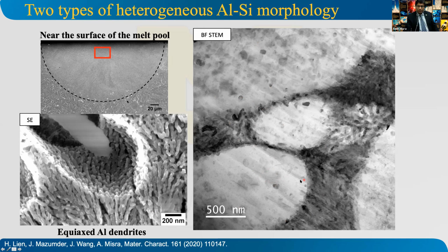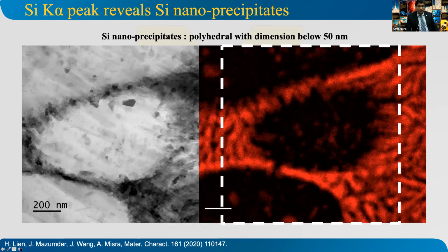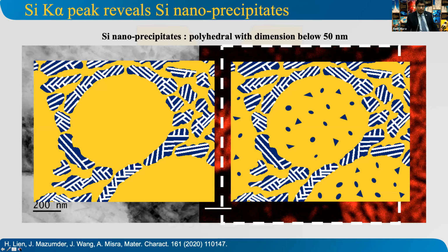So this is beginning to look like the structure I showed for copper moly, formed under very different kind of processing conditions, but it is hierarchical in nature. So you have a matrix defined by a eutectic structure, in this case of aluminum silicon fibers, where silicon fiber itself is nano-twinned, and having these islands of these coarse aluminum dendrites that internally contain silicon precipitation. So this is just showing that you have silicon precipitates.